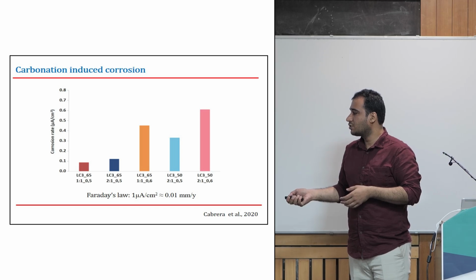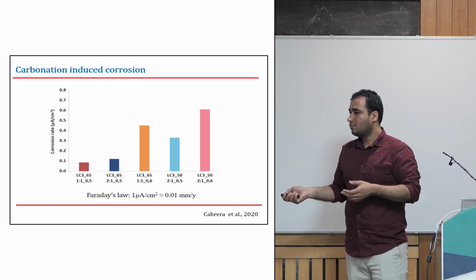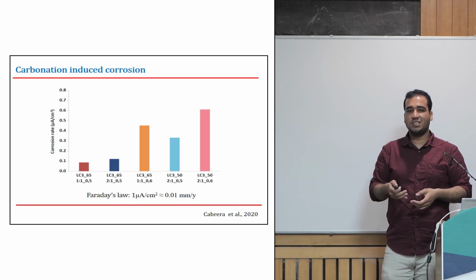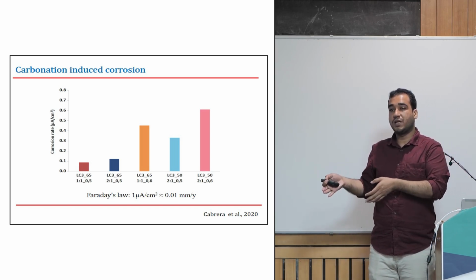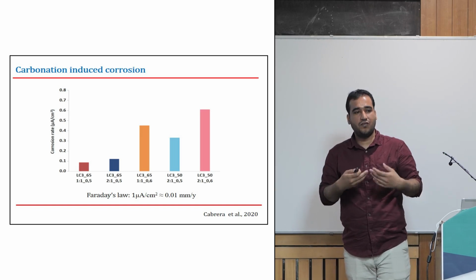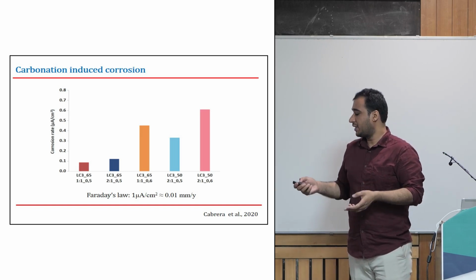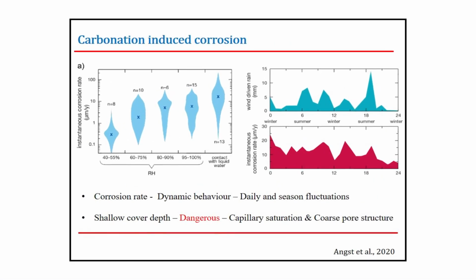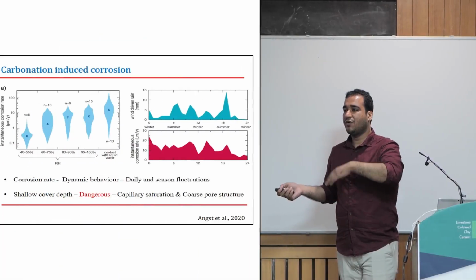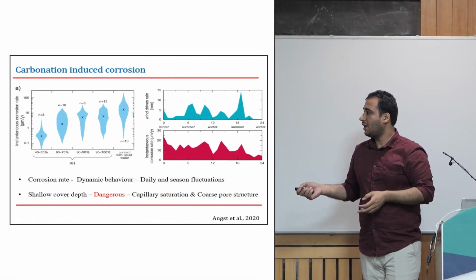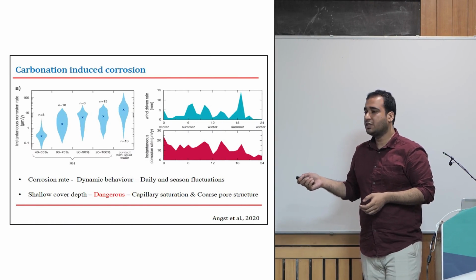But when you convert these values to millimeter per year, you see it's less than 0.01 millimeter per year. So you can see it's not that harmful for your structure as you would expect it to be. To elaborate on it more, there is a study that compiles the literature about how the corrosion rate changes at different relative humidities. Unlike chlorides, where the structure is in contact with the water, structures which are subjected to carbonation generally have a variation of the relative humidity. And at different relative humidities after carbonation, the corrosion rate can be different.